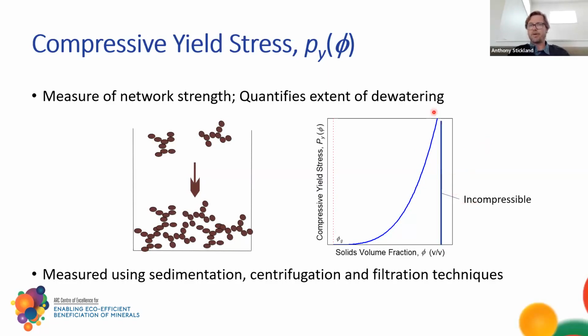If I have an incompressible material, it's just a straight line on this plot. The gel point is the same as its infinite compressibility, if you like. And so it's just a straight line up and down. Funnily enough, I haven't measured a material yet that is not compressible to some degree. I can do a sedimentation test on 250, 300 micron big balls of stuff, and I will still get a slightly different value when I do a sedimentation versus a filtration test.